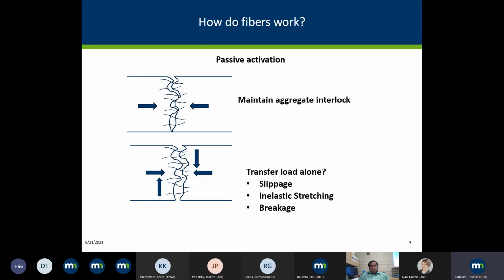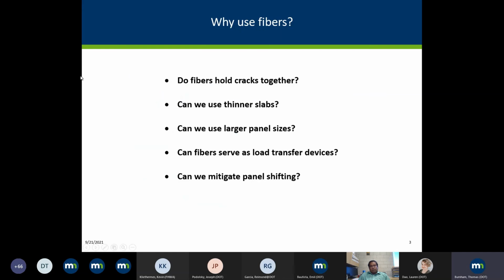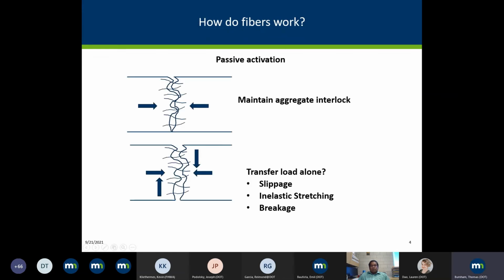If this is a saw joint, we want to keep the aggregate interlock action as long as we can. But over time, we know that several of the joints are going to separate wide enough that aggregate interlock is not available anymore. And then we want to know, can these fibers act alone to help transfer the load across the joint? But at the same time, because it's so wide, we have to worry about slippage of the fiber out of the concrete, inelastic stretching, so we can stretch it far enough and then the fiber becomes floppy within the gap, and also just breaking the fiber from the excessive forces.